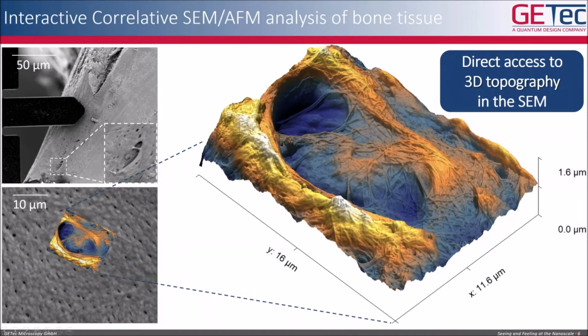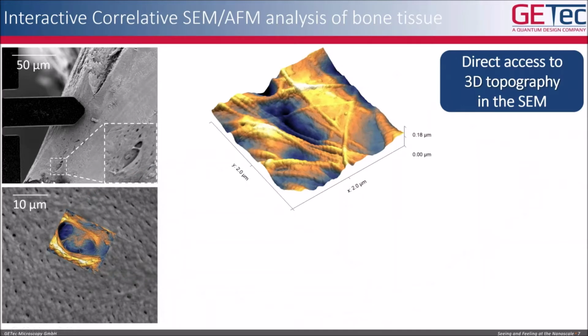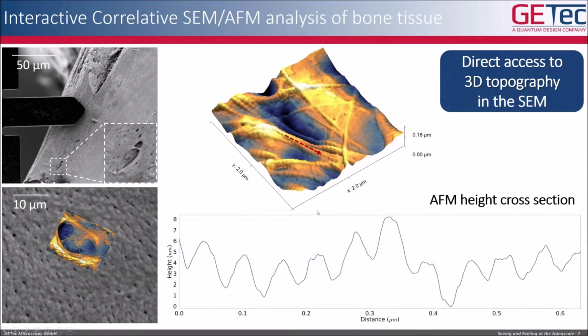You can also zoom into an area of interest, here where you have all these collagen fibers, take a high-resolution image that you can see here, and then extract a line profile from one of these collagen fibers marked here by this red line. If you look now at this line profile below, you can observe this typical ripple-like structure on top of this collagen fiber with a periodicity of around 67 nanometers.